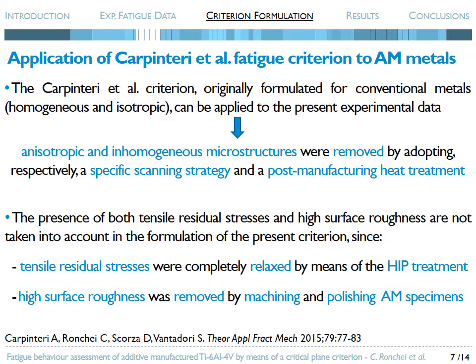a post-manufacturing heat treatment. Moreover, the presence of both tensile residual stresses and high surface roughness, which are peculiar features of AM metals, are not taken into account in the formulation of the present criterion, since tensile residual stresses were completely relaxed by means of the heat treatment. High surface roughness was removed by machining and polishing the AM specimens.